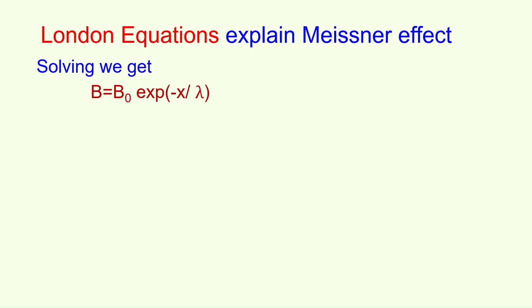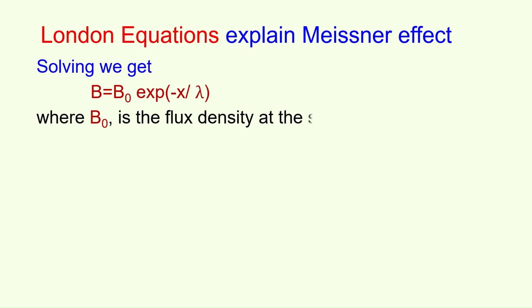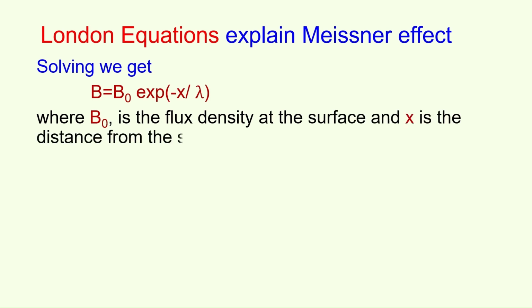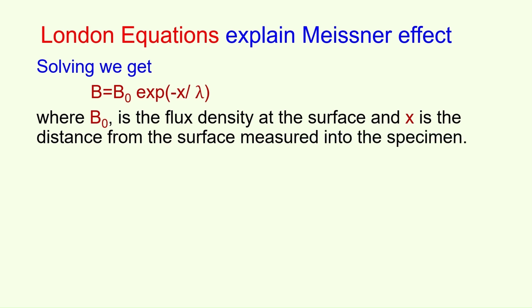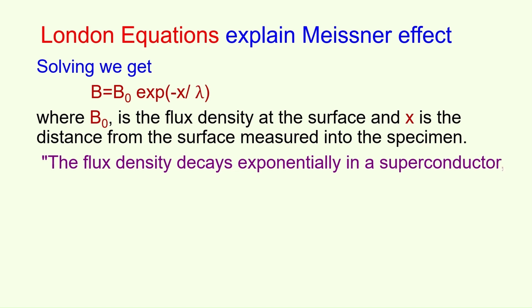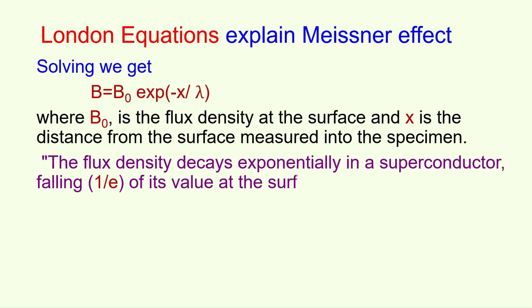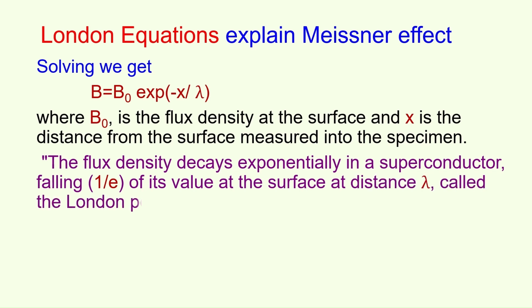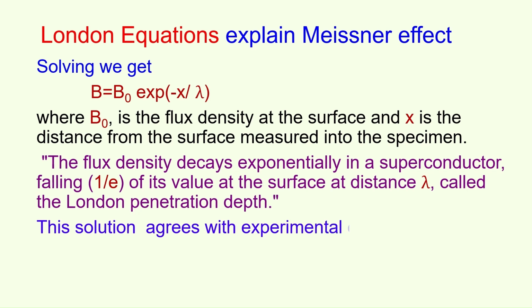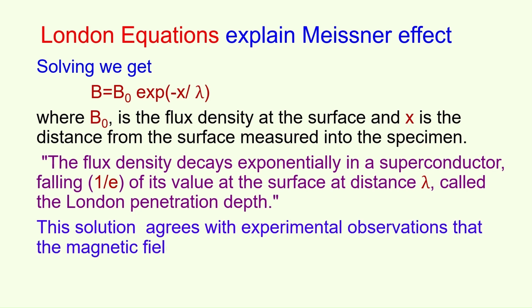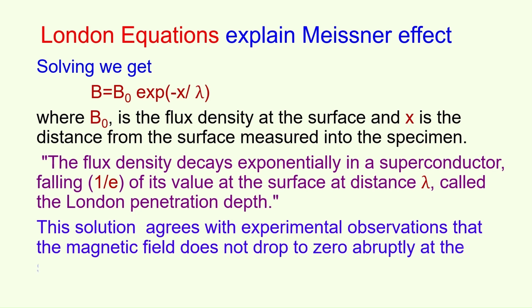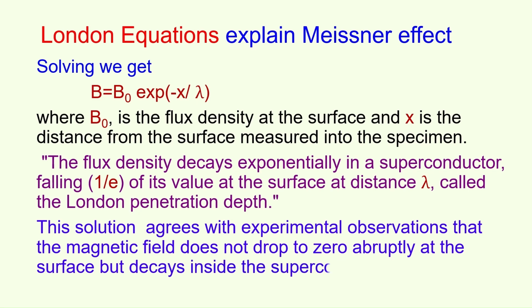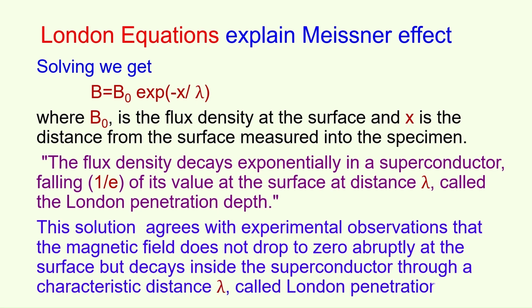Solving, we get B equals B0 exponential of minus x divided by lambda, where B0 is the flux density at the surface, and x is the distance from the surface measured into the specimen. The flux density decays exponentially in a superconductor, falling to 1 divided by e of its value at the surface at distance lambda, called the London penetration depth. This solution agrees with experimental observations that the magnetic field does not drop to 0 abruptly at the surface but decays inside the superconductor through a characteristic distance lambda, called the London penetration depth.